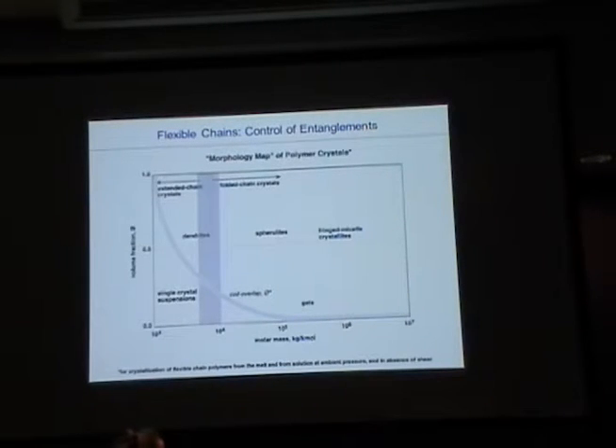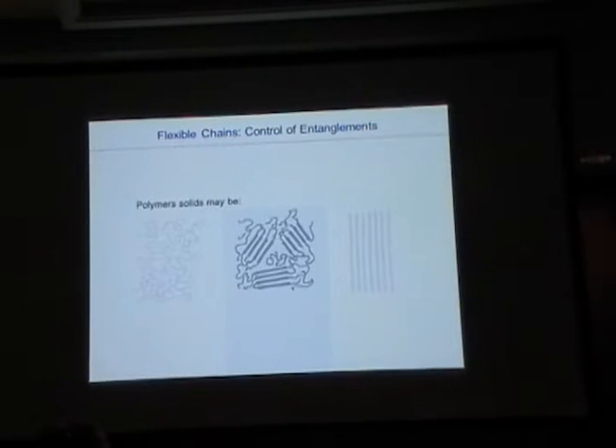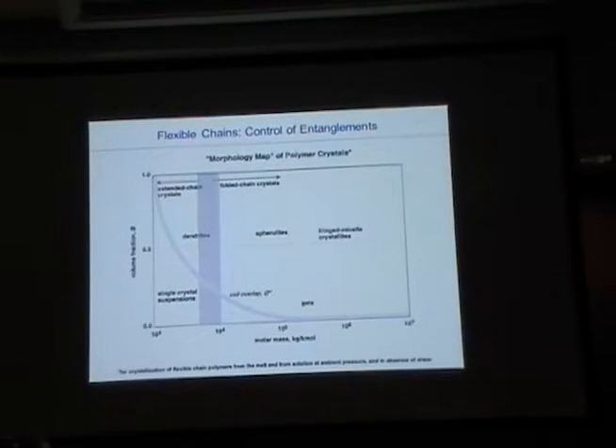So here we have a melt, so we have no solvent, and then we change the molecular weight. So in the beginning, even when we have very short chains, we don't have entanglements even in the melt. The molecules are just too short. It's like macaroni. If you make macaroni, it's very easy to eat. You don't need this fork and this is the spaghetti. So these are the macaronis of the polymers. In the melt, they form, if you're lucky, extended chain crystals.